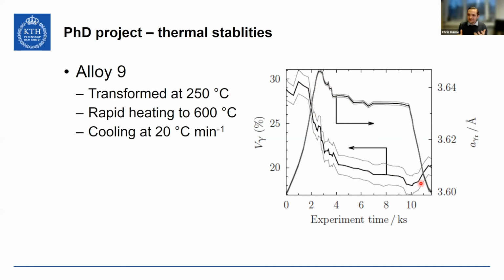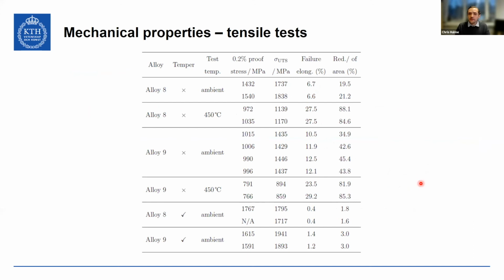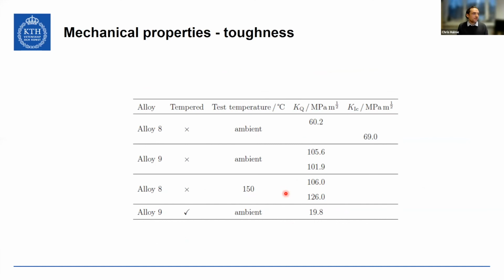We also had some requirements of the strength and fatigue resistance and the toughness. And if you look at the strength of these alloys, we just take the UTS, just to give you a quick marker here because we're quite short on time. Alloy 8, even at temperature, was still over 1 gigapascal UTS, which was way above what they needed. And alloy 9, almost 850, 900, again above what was required, which was very good for the project. And if we look at the toughness, actually alloy 9 was so tough it could hardly be measured. We couldn't get a K1C reading for most of these because the toughness was just too high. So there wasn't a valid K1C test. We could get a measure, they call that KQ, and it's still very high, much higher than what Rolls-Royce wanted.